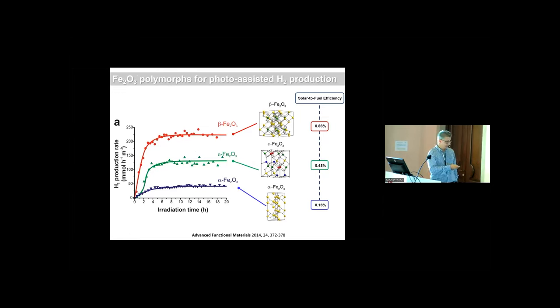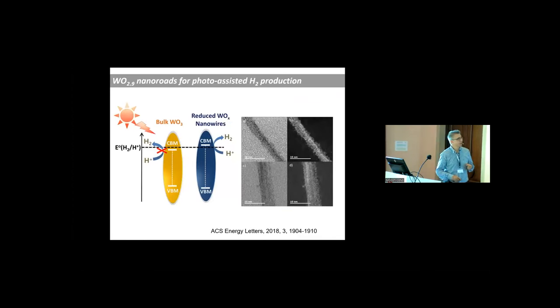You can see this is stable rates with time. There is an induction period, different polymorphs, different rates. It depends on the absorption of the surfactant agent on the surface of these materials. The solar to fuel efficiencies, you can see here, are very poor. So this is a proof of concept more than any possible solution to the energy demand that we have today.